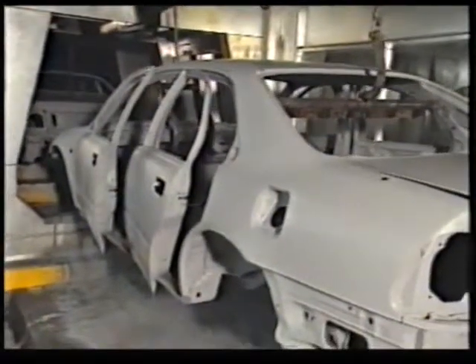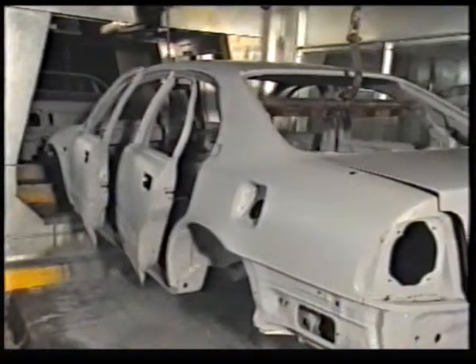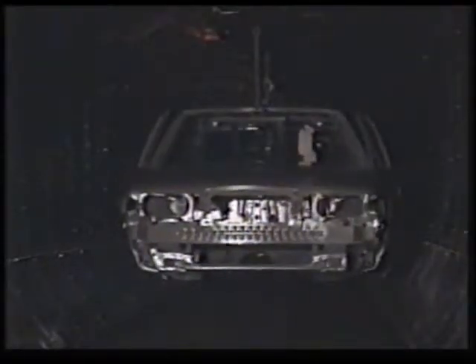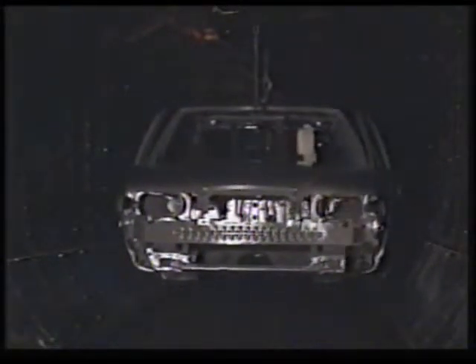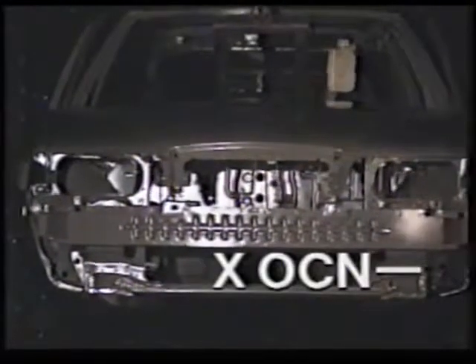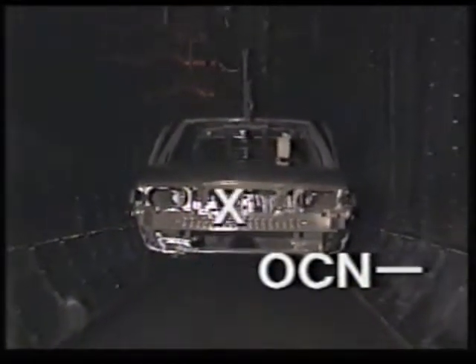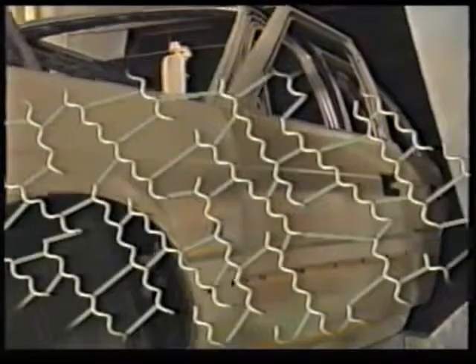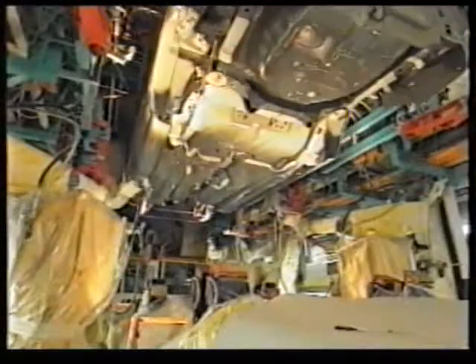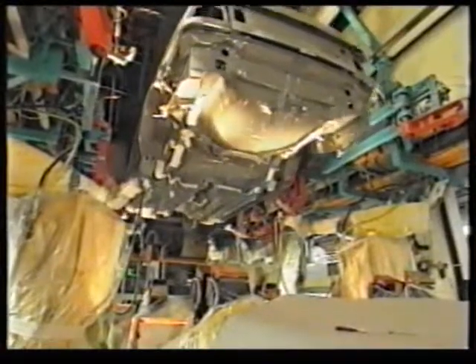Then the vehicle moves into an oven where some clever chemistry occurs. First, the paint monomer flows. This will eventually give the electrocoat its smooth, even finish. Then at about 160 degrees centigrade, isocyanate groups on the hydrocarbon chain become unblocked and free to react with the hydroxyl groups. 10 to 15 minutes at 175 degrees centigrade is all that it takes to make these chemical crosslinks and form the electrocoat polymer. The car moves on to the next